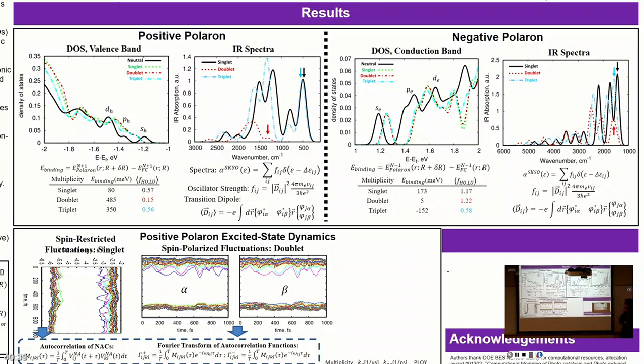Yeah, and comparing that to other results in the literature, they found for a similar model for computation that their binding energies were on the order of electron volts consistently, so like 1 eV. But the main difference is that they had an actual cluster. They didn't have ligands, so you could possibly argue that ligands suppress some of the nuclear reorganization at the surface, but there's probably a little bit more at play. There's probably a miscalculation somewhere too, so I just have to go back and double check those.